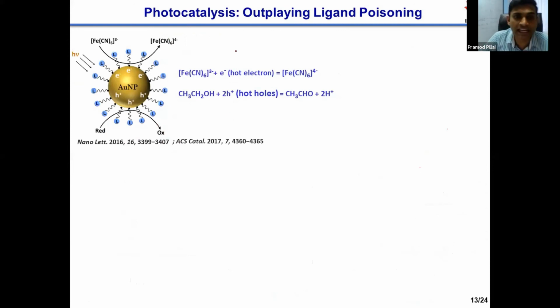So then we went to another class of reaction which I have explained earlier, which is the photocatalysis, where the nanoparticles are actively participating in catalysis. So one of the model reactions for this is the 1 electron reduction of ferricyanide to ferrocyanide, and here we use ethanol as the hole scavenger. So the mechanism is as follows: you excite the nanoparticle, you generate the hot electrons and hot holes. The electrons will be used for the reduction, and the holes will be consumed by the hole scavenger, thereby regenerating the catalyst, so that we can do it for multiple cycles.